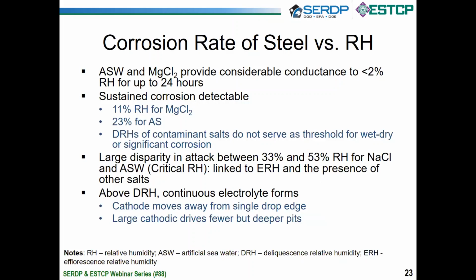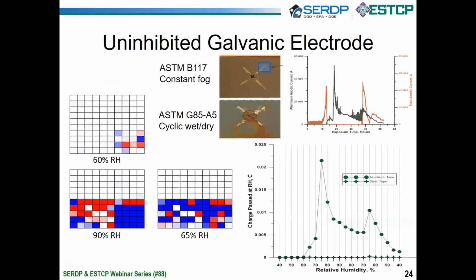To summarize all of that, if you just looked at magnesium chloride, you can have corrosion going on down to 11%. And if you load up enough artificial seawater in this, corrosion can happen down at 23%. Again, it's very low, but it happens. But there's a large disparity of attack. So again, corrosion happens under the deliquescence point, and the morphology, what that corrosion looks like, is very different under the deliquescence point than above it.